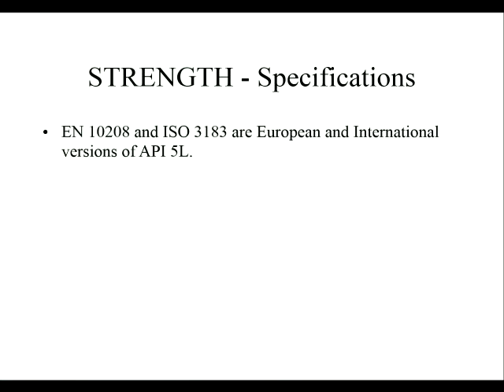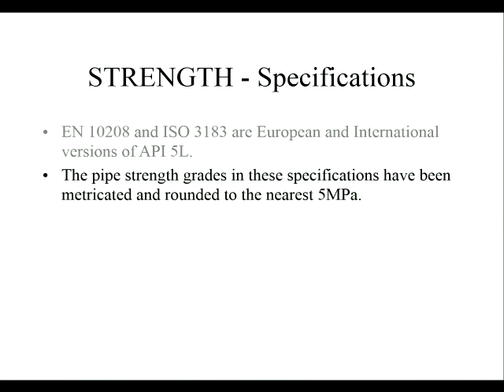Now, of course, the Americans have a standard, there's an international standard, and it's almost the same, but not quite. So the European standard 10208 and the ISO 3183 are just the European and international versions of the API 5L. But because standardisation people like to work in more straightforward systems, they metricate the API 5L versions and they convert them or round them to the nearest 5 megapascals. So an ISO 3183 and an API 5L steel are not quite the same. They're almost the same, but they're not. So if you're working to one standard, make sure you're working to that standard and not the other one. Know which one you're doing.